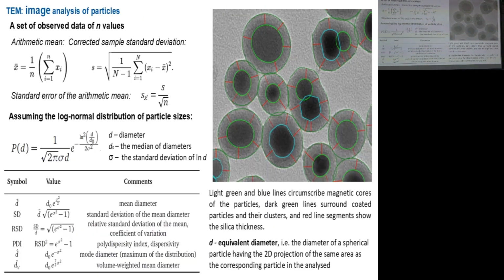Maybe you will go for some image analysis. You would like to describe your sample, the sizes in some quantitative manner. So the data are definitely useful for that, and what to analyze, what to report. All the time I suggest to calculate the arithmetic mean. Do not, like in the first stage, do not make any assumption about the distribution. And also in your papers, it's really better to include just the arithmetic means, just some descriptive statistics of your sample before going to some assumptions regarding the size distribution. So you can measure some particles in your images. There are many programs to do it.